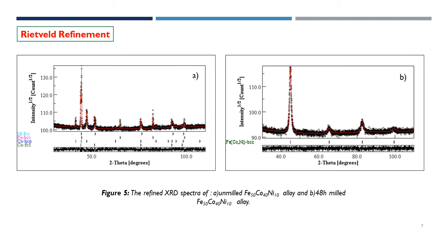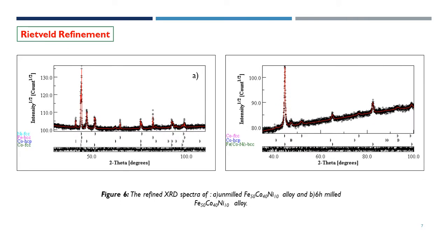fitted by the MAUD program using the Rietveld method before milling and after 48 hours of milling. The refinement results confirm the formation of the body-centered cubic iron-cobalt-nickel solid solution. It was also noted that the proportions of the hexagonal cobalt and the face-centered cobalt phases manifest an opposite trend. However, both phases disappear totally above 6 hours of milling.